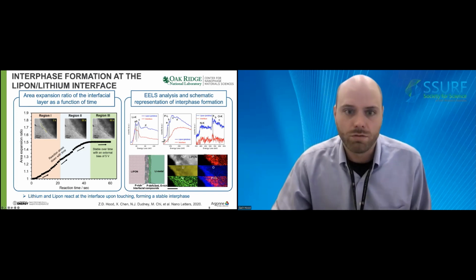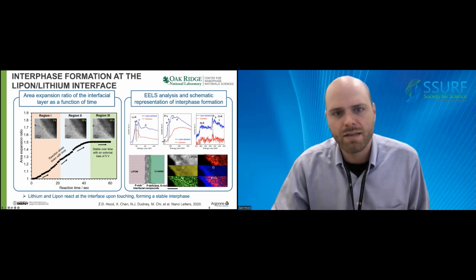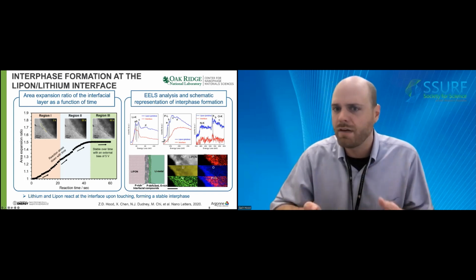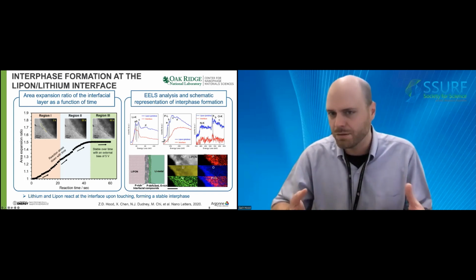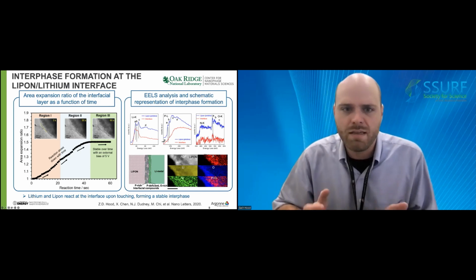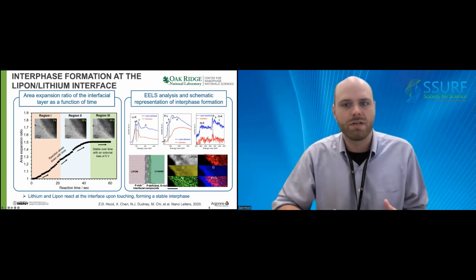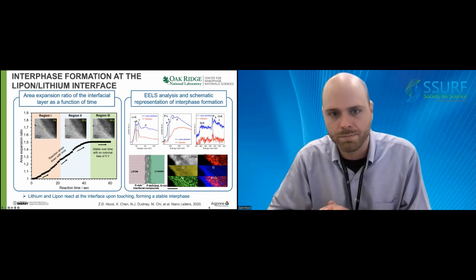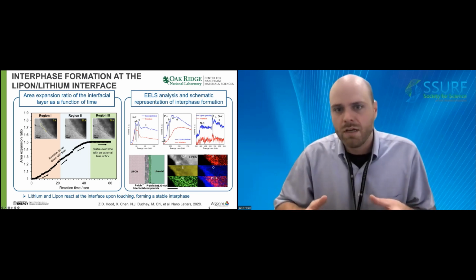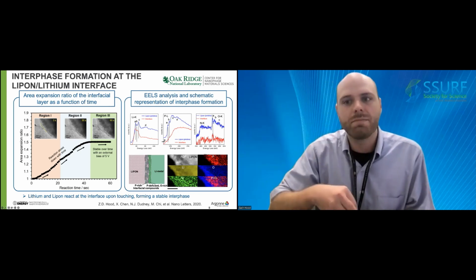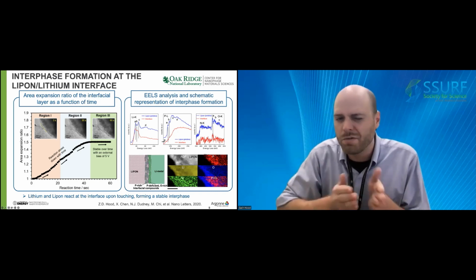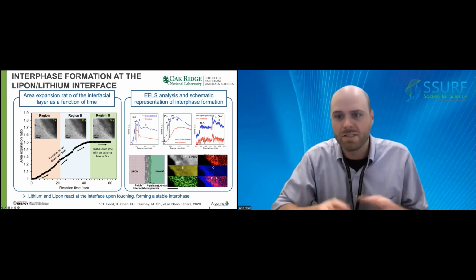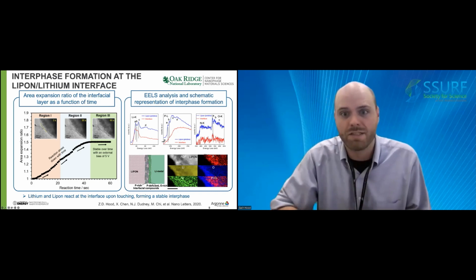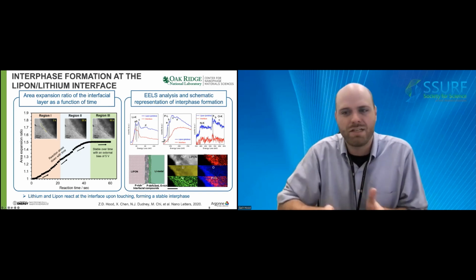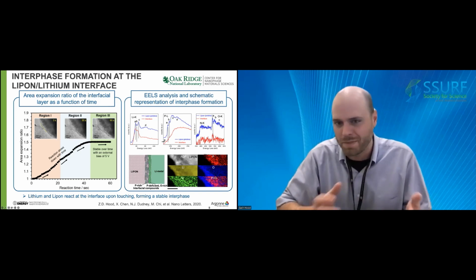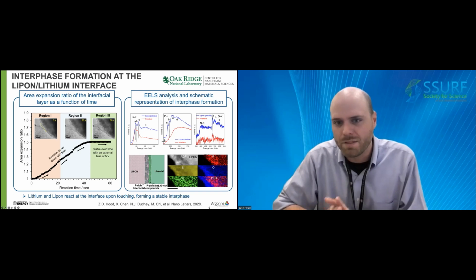bias of 5 volts. To further interrogate this interface, we applied electron energy loss spectroscopy, known as EELS, to better understand the chemistry and the electronic structure of the interface formation. So using EELS, a material is essentially exposed to a beam of electrons with a known narrow range of kinetic energies. And some of the electrons will undergo inelastic scattering, which means that they lose energy and have their paths slightly and randomly deflected by the material.